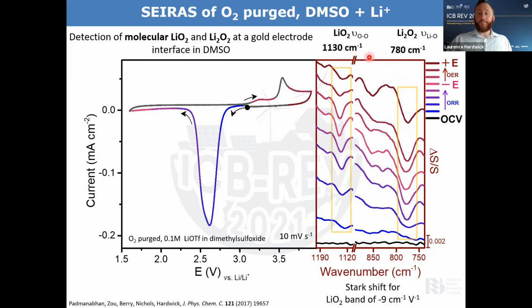These positions, 780 and 1130, these bands can be assigned to molecular lithium superoxide and molecular lithium peroxide, and this is very interesting. Due to selection rules, if you had the crystalline lithium peroxide, this band would be silent. In the molecular form, we do see this band, so we're able to see molecular species at the interface. We also have evidence of adsorbed species, particularly of the lithium superoxide, because there's what's known as a Stark shift. These bands are very sensitive to the change in potential, and so will shift in position. This indicates that our species are certainly within the field and adsorbed close to the electrode interface.